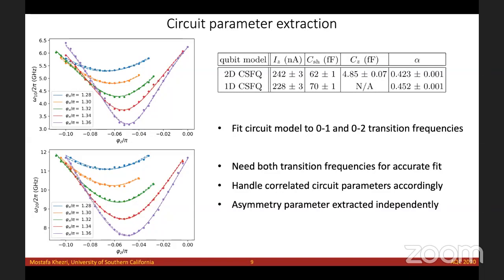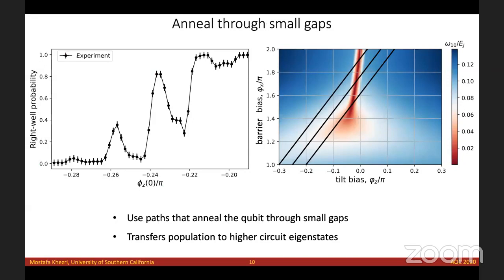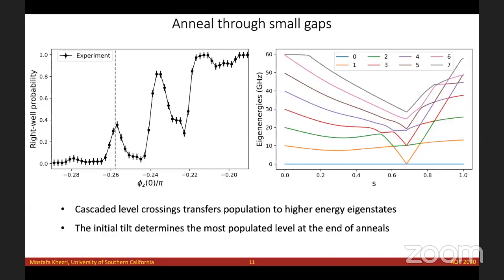So let's keep this fitted model in mind because we're going to use it later. We can essentially try to play with these annealing paths a little bit. For example, we can use these black line annealing paths to intentionally close the qubit gap as we're annealing the qubit, and just perform a persistent current readout measurement at the end. And then you can see we end up with this strange looking plot with these peaks and features and everything. But we can actually use this plot to investigate the multi-level structure of our circuit and validate our circuit model.